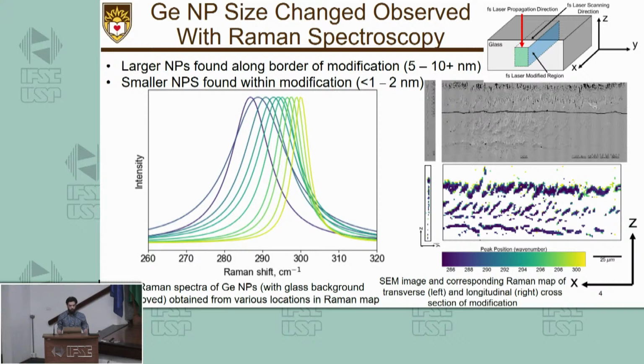And another interesting note that we see when we make these modifications is that the peak of germanium nanoparticles will shift. Based on Raman spectroscopy and the phonon confinement model, that indicates that the nanoparticles are changing in size. So that gives us promise to be able to better control the size of the nanoparticles to try to make a more continuous channel of them. And you can see in the bottom right figure, looking along the length of the line, we're almost continuous. So we're very optimistic about what we'll be able to achieve. With that, thank you.